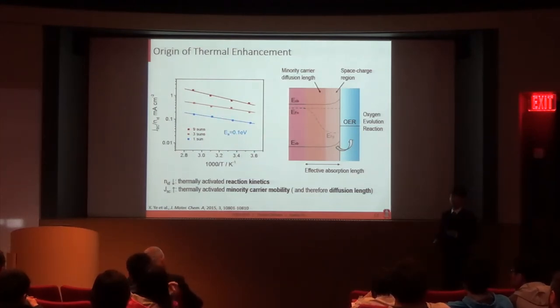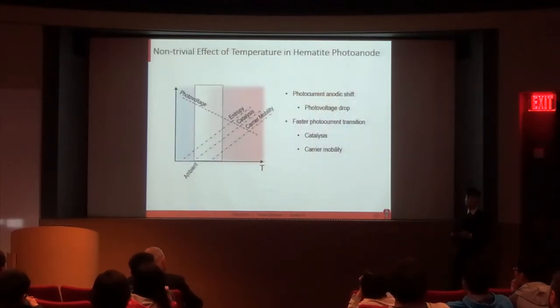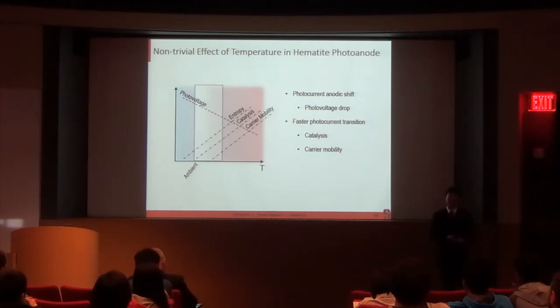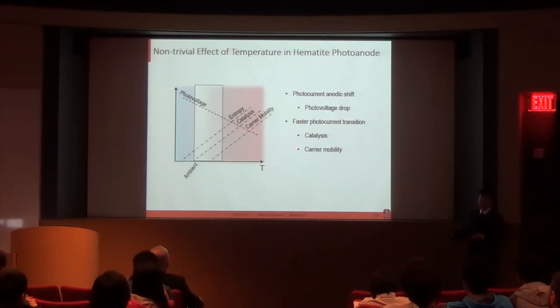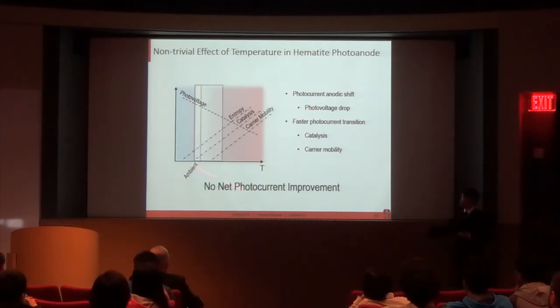the photocurrent transition. So in a brief summary, with the help of the hematite photoanode, we clearly see how temperature affects the photoelectrochemical cell in different ways. The photocurrent anodic shift indicates a photovoltage drop with increasing temperature, while the faster photocurrent transition can be attributed to a combined effect of both catalysis and carrier mobility. But as we said, there's no net photocurrent improvement in this hematite photoanode.